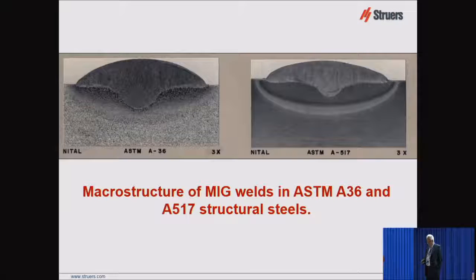Here's some additional shots of this A36 structural steel on the left, A517 on the right, two different welds here. And you can see the pattern here of the penetration of the weld. There's not a lot of depth of penetration below this surface over here, but there's good depth of penetration here. The heat affected zone is less pronounced here than it is over here. A36 is just garden variety, like 1020 carbon steel. And it was an alloy that was created back, I think, in the 1920s, or maybe even a little earlier. Been around forever. And 517 is a more modern, higher strength structural steel.